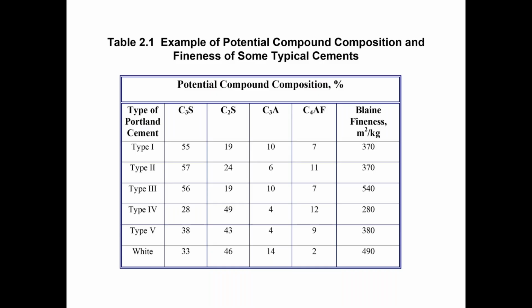Look at the white cement. So a few things to notice in the white cement. One is that it has a relatively low C3S content. So that means that C3S is one of our primary contributors to early strength gain. So to kind of offset the low C3S, we have a high Blaine fineness. So the low C3S would indicate a lower early strength gain, but the higher Blaine fineness would indicate a higher early strength gain. So those two are kind of canceling each other out, so that we're kind of middle of the road when it comes to early strength gain.